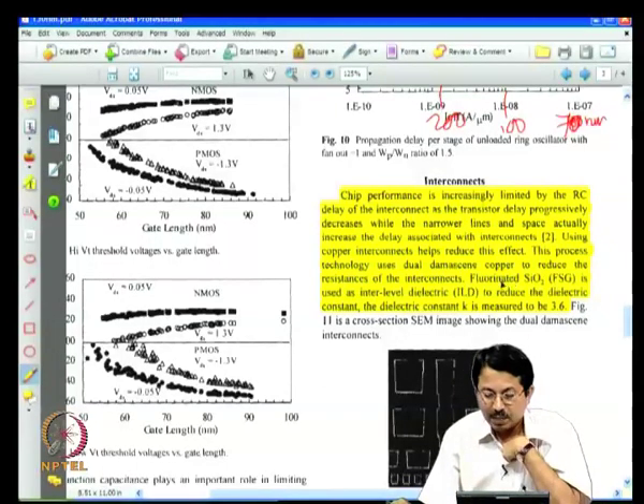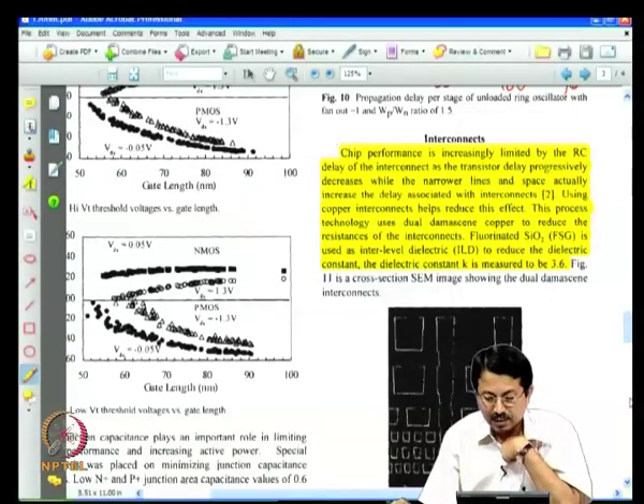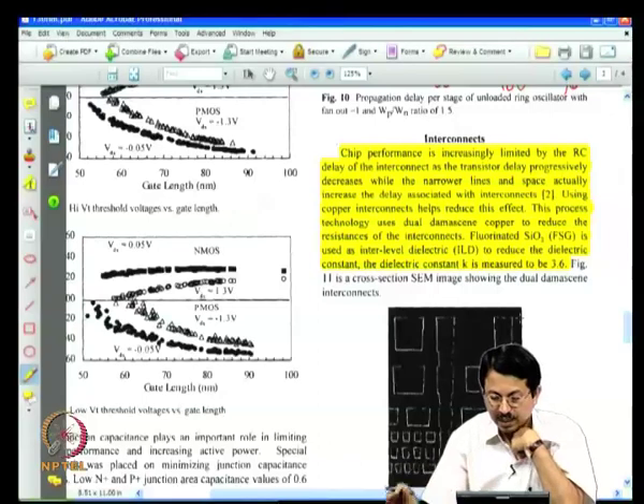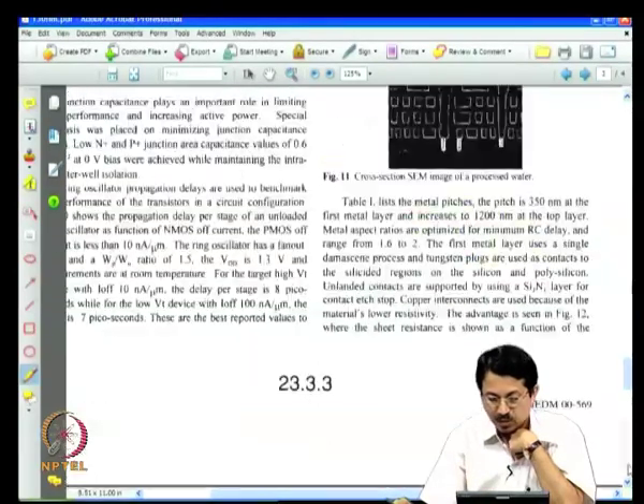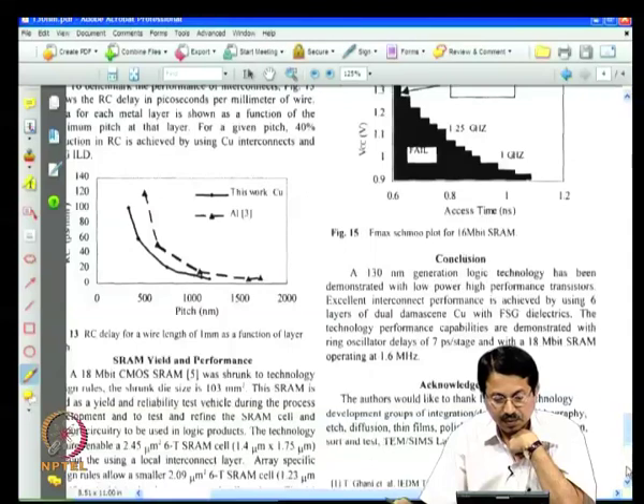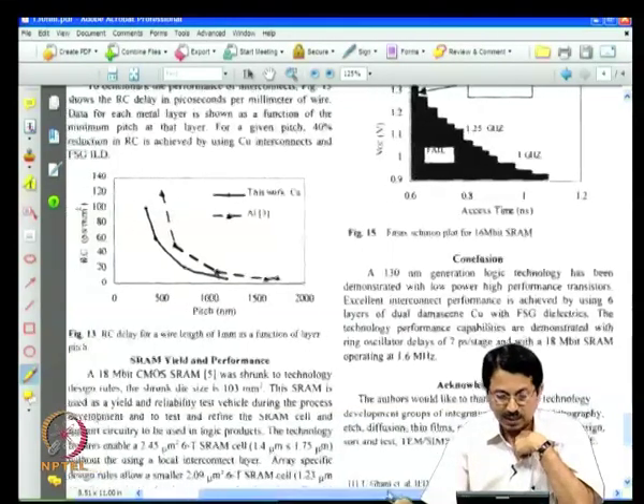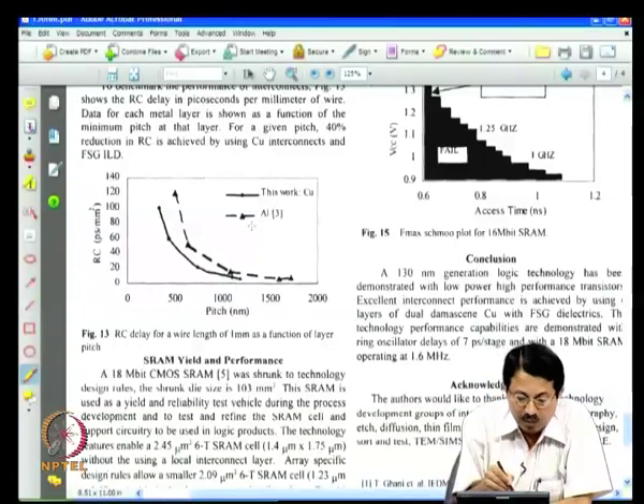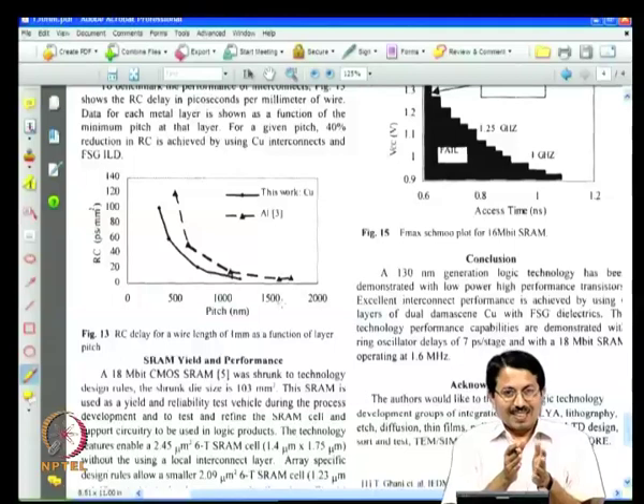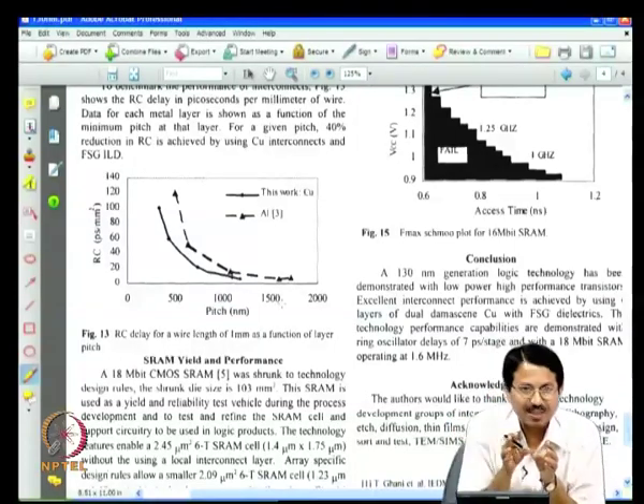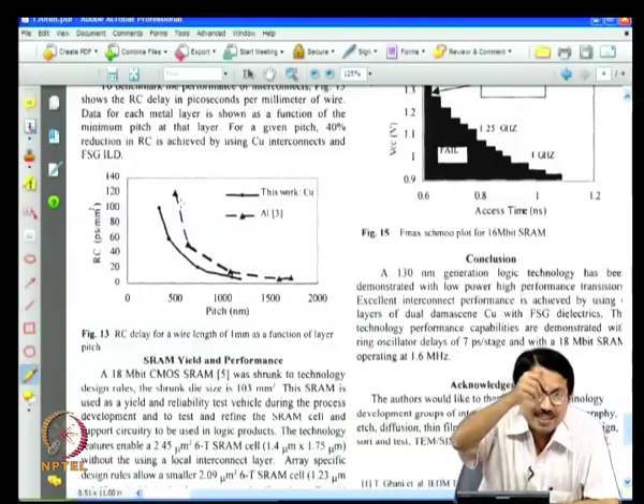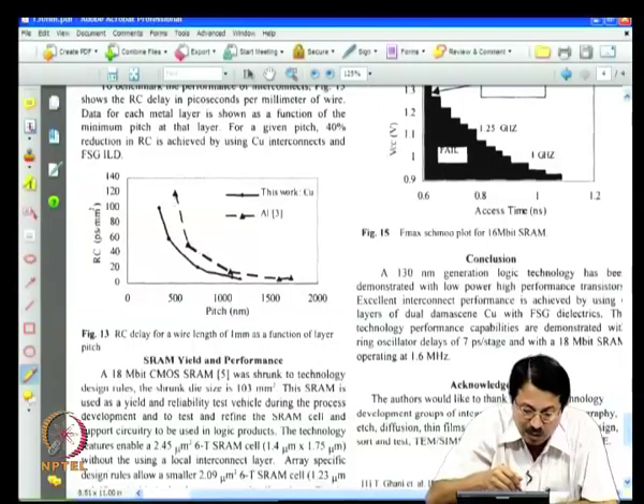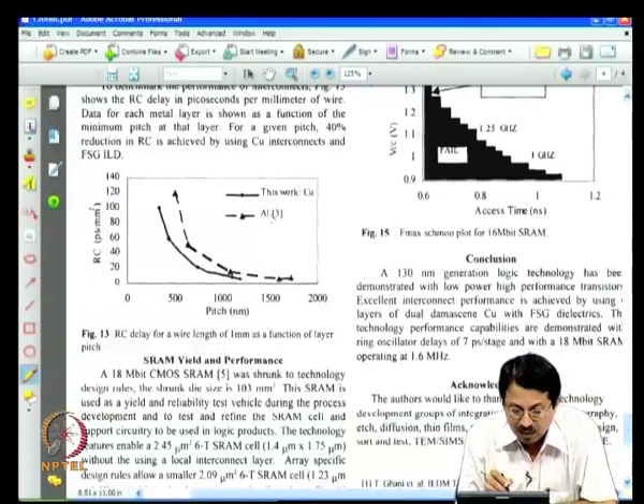And they have optimized this fluorinated oxide, and that gives a K of about 3.6, and this is again the hierarchy of interconnects, and they have used this to build. What they are showing here is that if they had used aluminum, with decreasing pitch, as two metals are coming closer to each other, your delays are increasing. If you had used aluminum, it would have gone up like this. Because you use copper, you could decrease it.